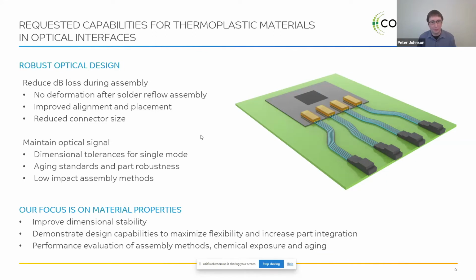Once you've actually made the part, though, the key component is maintaining that optical signal. We can't have it break once you've fully assembled the component, because that might risk the component needing to be tossed. So we want to maintain that through dimensional tolerances, even in single mode operations, have aging standards and material performance that's really robust, and then low impact assembly methods. So the more we can pre-assemble or simplify the process down, the better yield and the more robust the connector will be in the end.